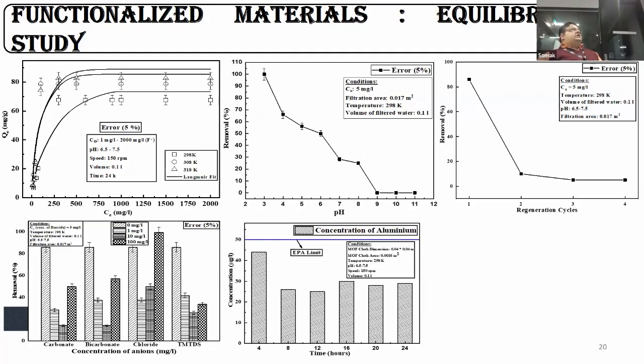Now, in case of removal, we studied with pH and were able to see that the ZPC is near the acidic range of 3 or 4. When it's greater than 4, the surface being negative repels fluoride, whereas if it's lesser than 4, the surface being positive attracts fluoride. We also studied the regeneration cycle, but in this case, with the MOF cloth, the regeneration completely diminishes after the second or third cycle.